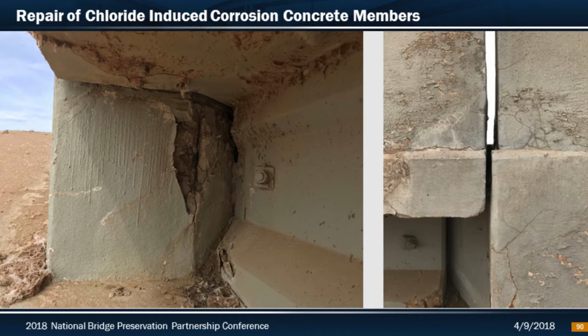Here was a back wall that was repaired in that original project. Obviously, due to location, we couldn't wrap it. So, again, the concerns with the repairs not lasting for long was pretty much validated by this photo here. After 20 years, or a little less than 20 years, the repair's already fallen apart and really not doing any good anymore. We all talk about the bonding of that externally bonded CFRP.